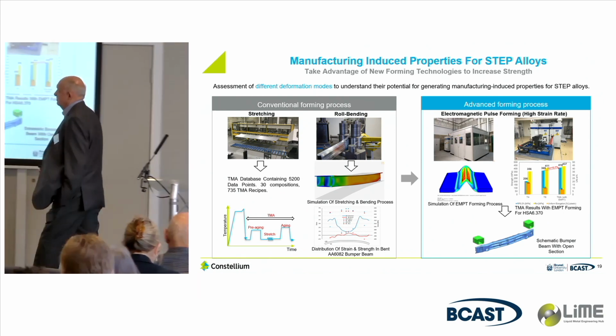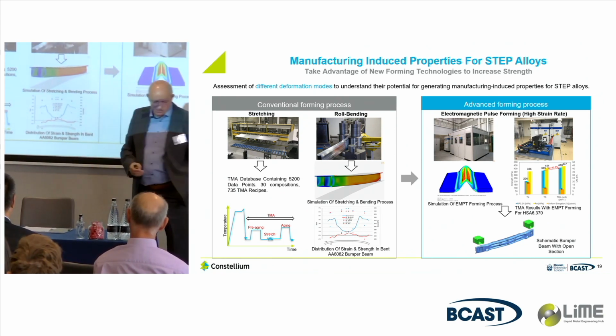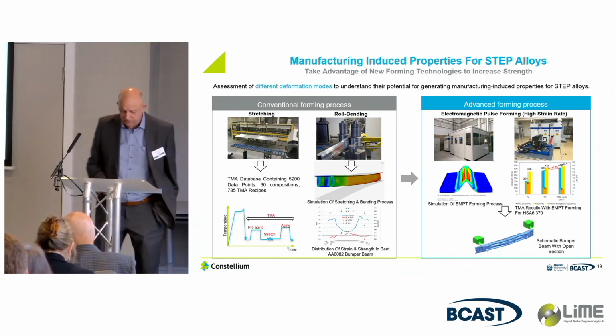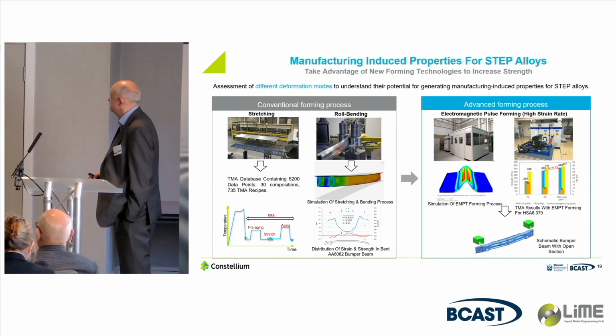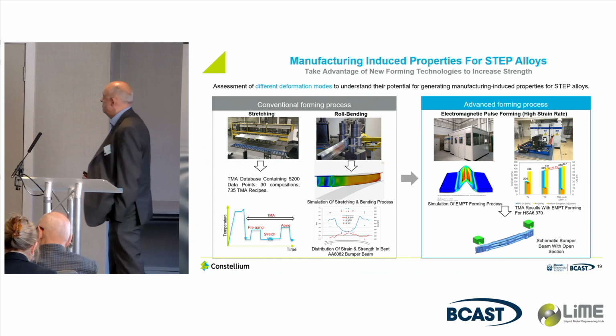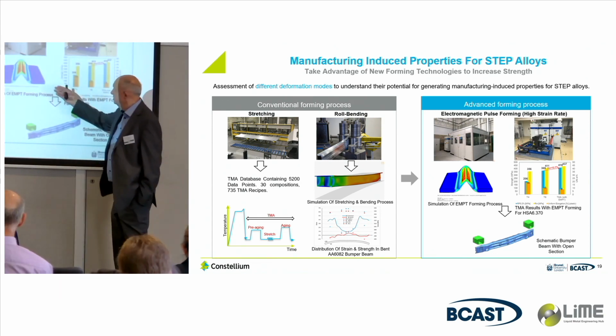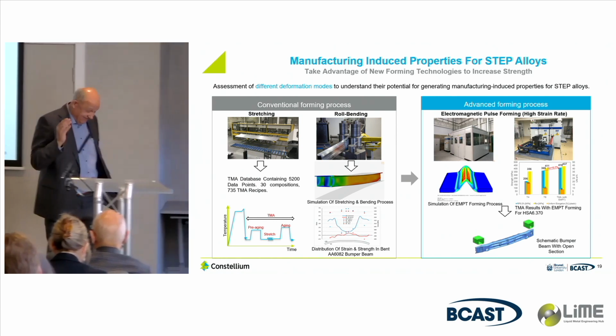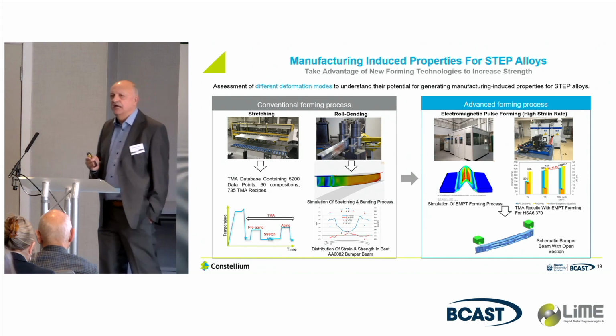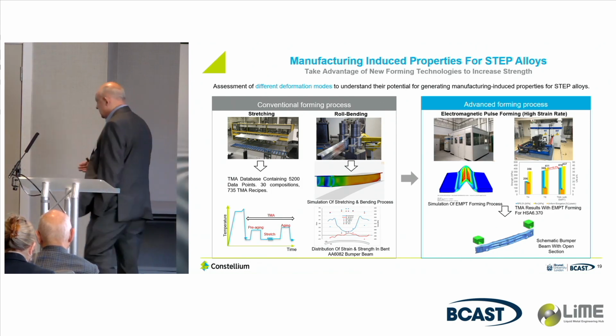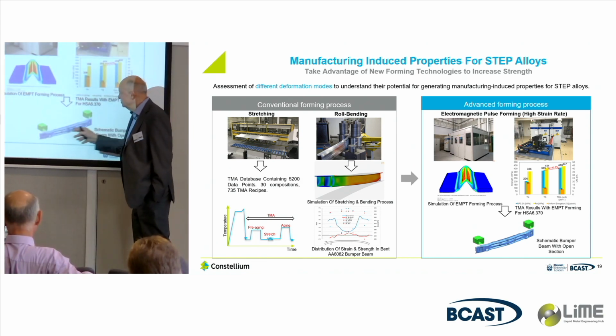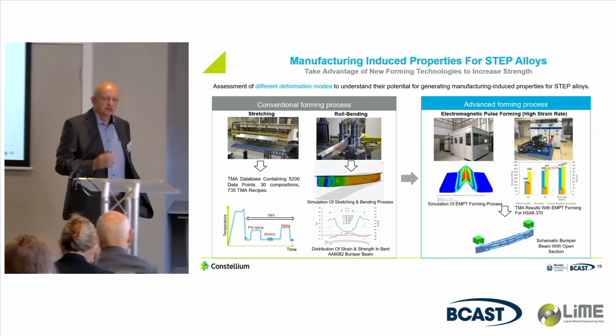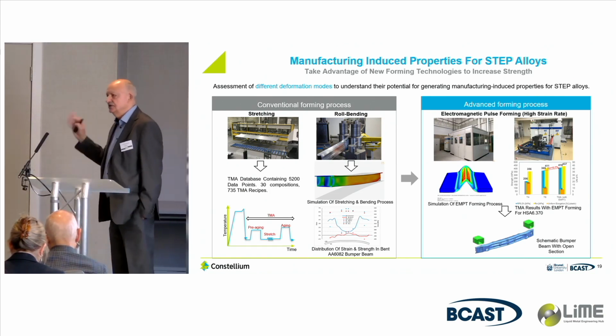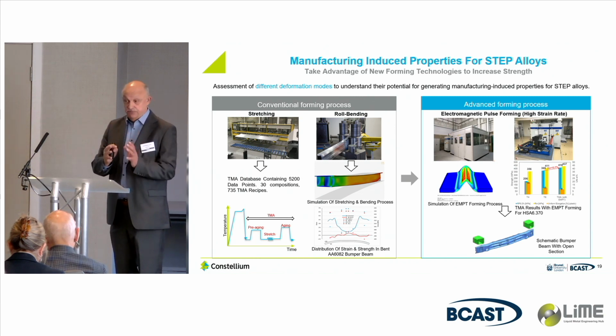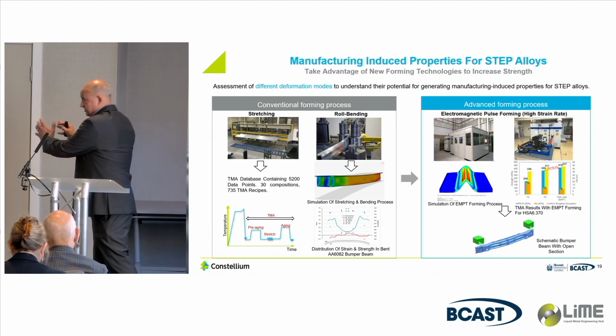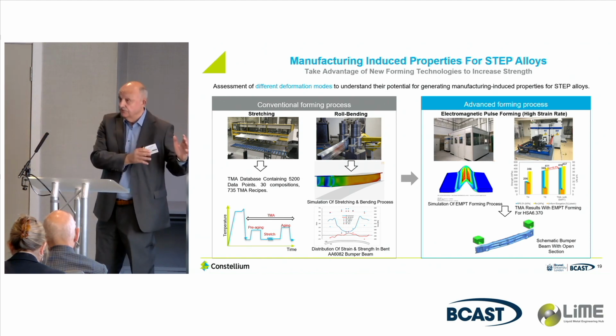This is fairly simple processes. This is stretching and bending. What can we do with just simple stretching and bending? And because we've got the availability of the electromagnetic pulse forming capability, we can get much higher levels of strain, which we do using this equipment, and potentially that's probably not going to be that useful for a front crash management system, but it could be particularly useful for a rear crash management system, which is a much more simple type structure, and the intrusion at the rear is much, much less. So it's about understanding how we can apply the STEP process to, in this case, a rear system, and what we need to do for a front system.